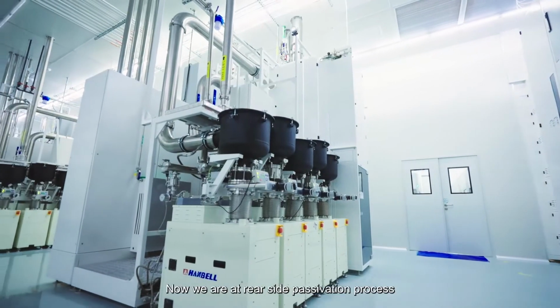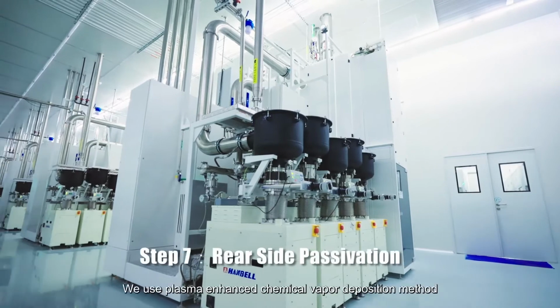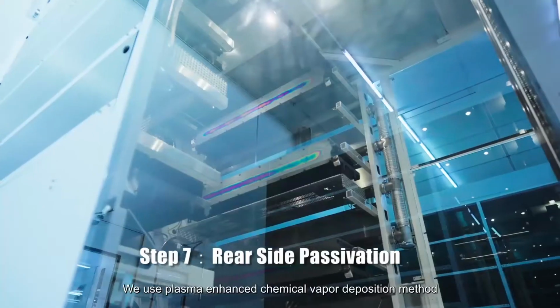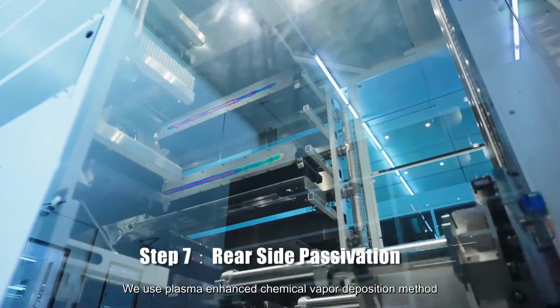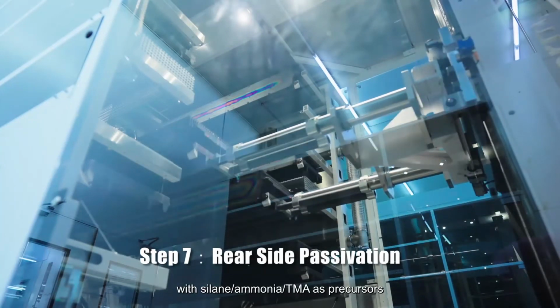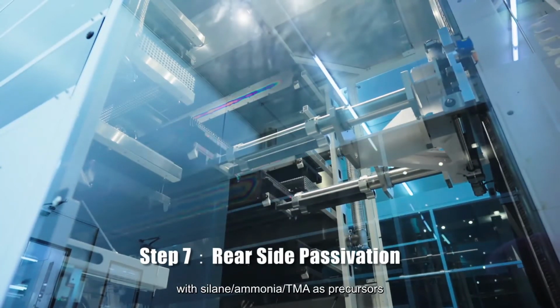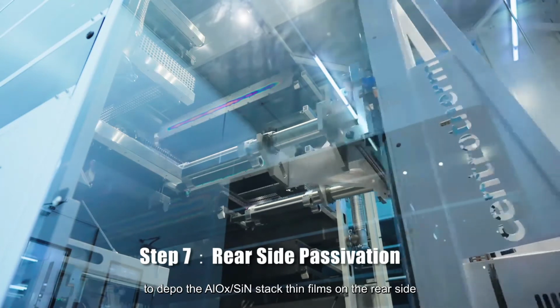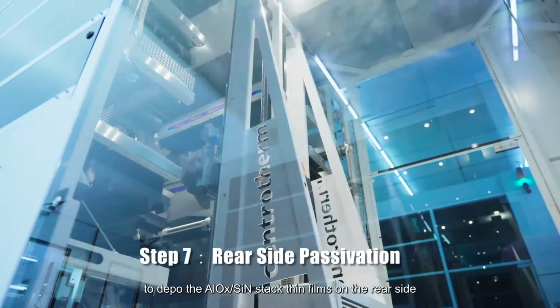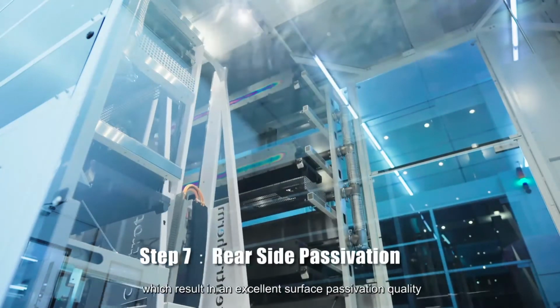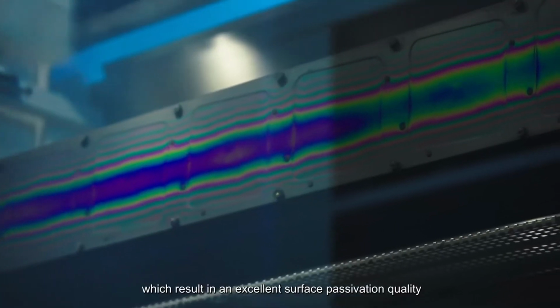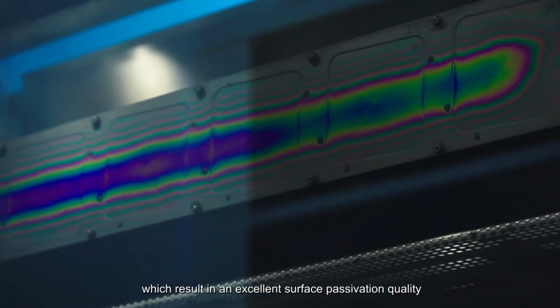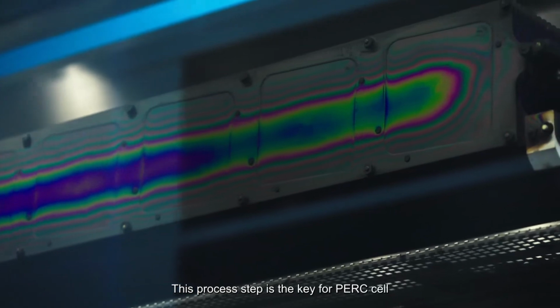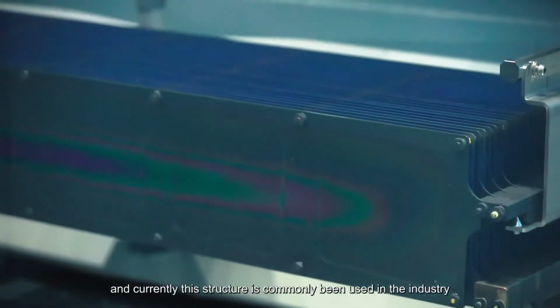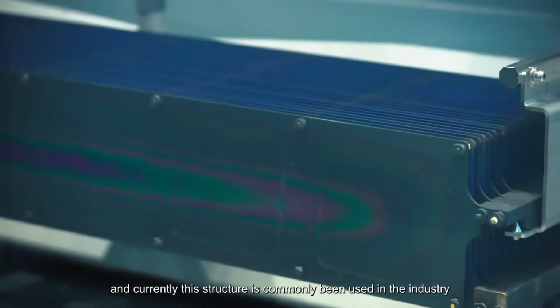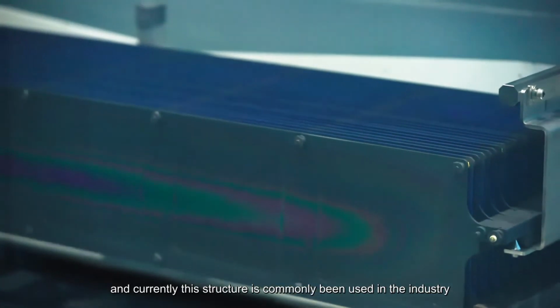Now we are at the rear side passivation process. We use the plasma enhanced chemical vapor deposition method with silane, ammonia, and TMA as precursors to deposit the aluminum oxide and silicon nitride stacked thin films on the rear side, which results in an excellent surface passivation quality. This process step is the key for the PERC cell and currently this structure is commonly used in the industry.